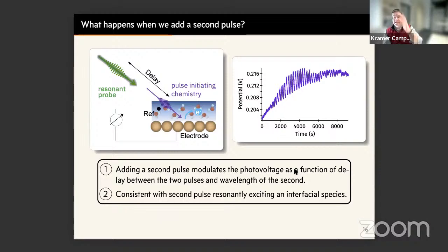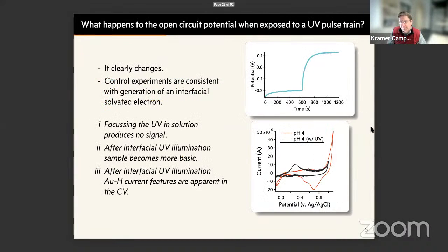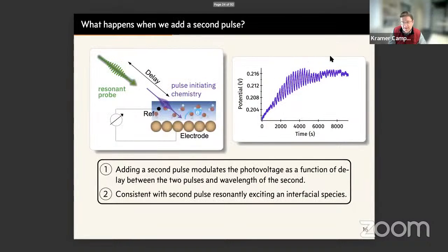Okay, so this is the first pulse, but of course I told you we do 2 photon photovoltage. And what you do here now is you wait till the sample is stabilized, say up here at about 1,000 seconds. And now you add a second pulse train at a variable photon energy. And if you do that and scan the thing as a function of delay between 2 pulses, you produce data that looks like this.